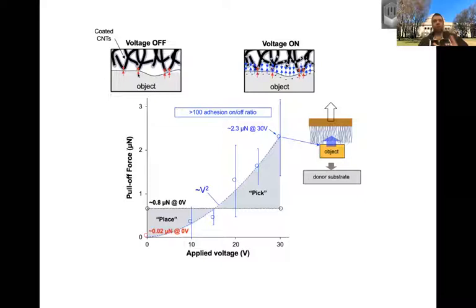So you have a surface that has electrostatically switchable adhesion because of the charging effect, but also has very low off-state adhesion because the contact area is very, very small. The CNTs are very sparse. And by tuning this, studying this, it means we can pick things up with a high attraction force, but then we can turn off the voltage and set them down. So small things, which don't weigh very much, don't stick to the stamp unless the voltage is on.